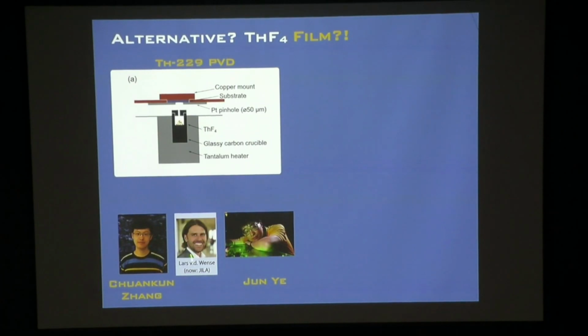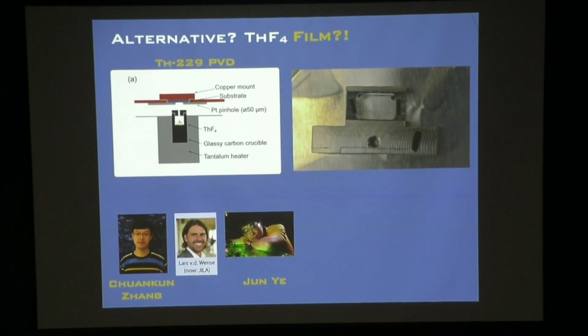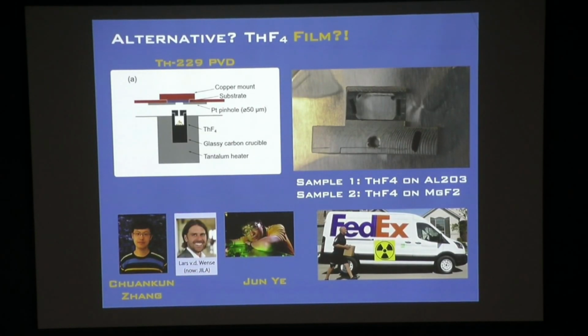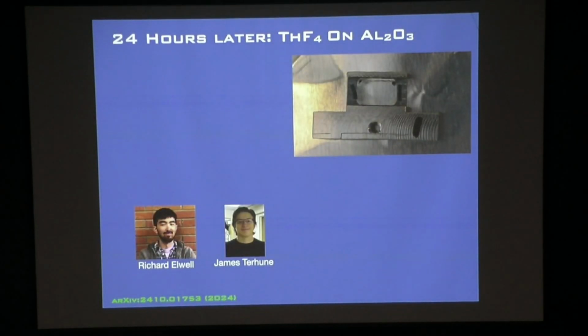And so June's grad student now, who inherited this, Chungkun, once we found the transition, said, hey, I can make you guys a thorium fluoride thin film. And we're like, okay, we'll try it. That's crazy. It's not a crystal. It's going to be polycrystalline and probably all quenched, but might as well try. So Chungkun made it in a few hours. He coated thorium fluoride on some sapphire and on MgF2, and this is what it looks like. This is, say, a little sapphire window, and there's maybe 100 nanometers of thorium fluoride on there. FedEx will ship anything, so they took this, and in 24 hours, we had it in our lab.